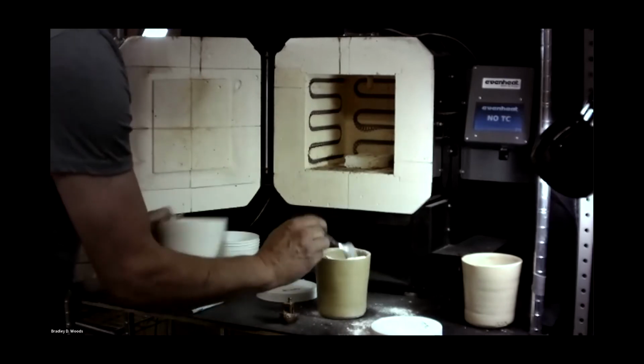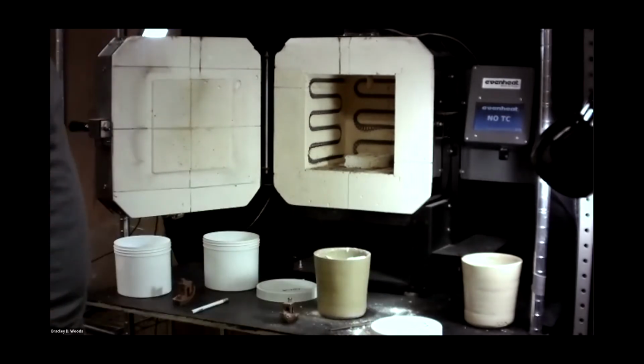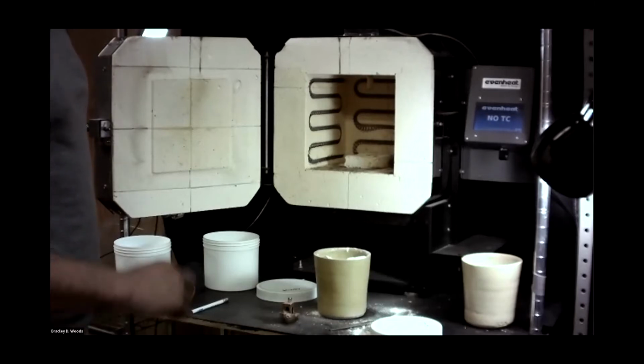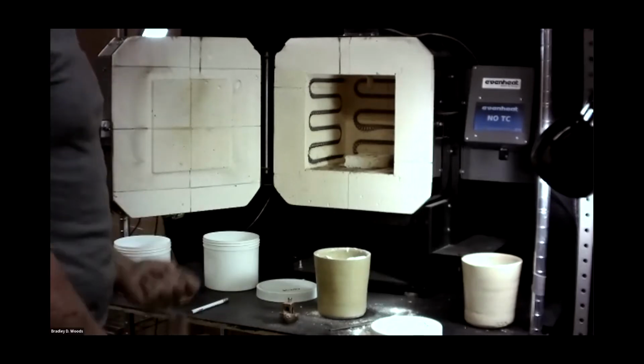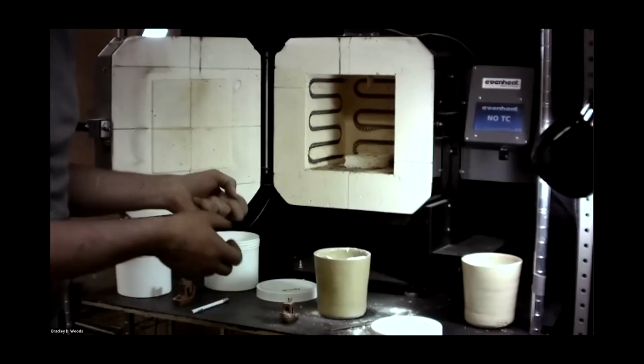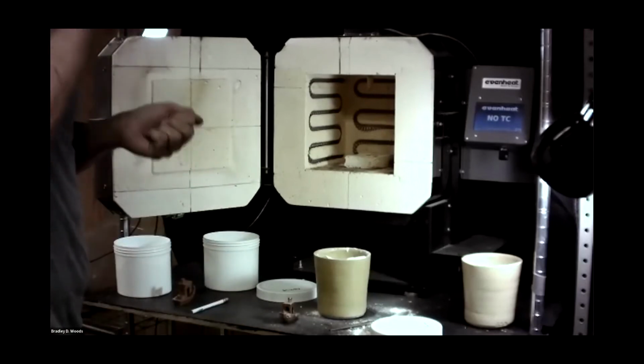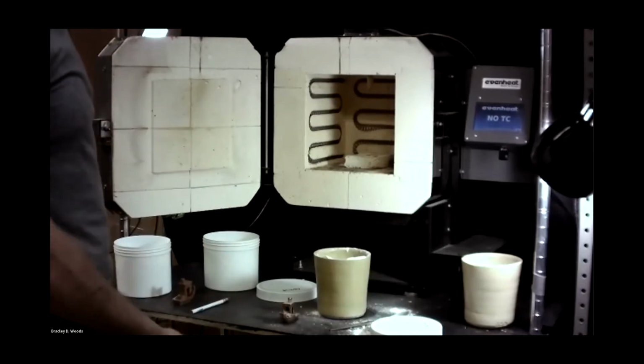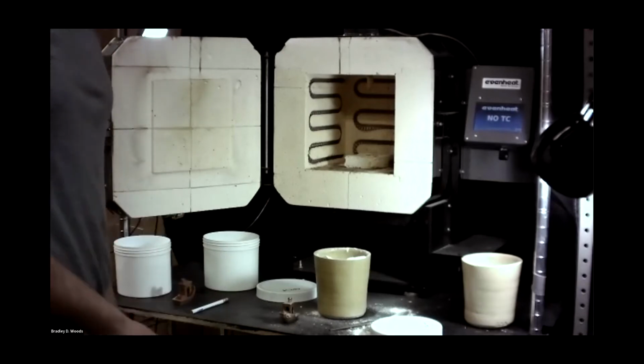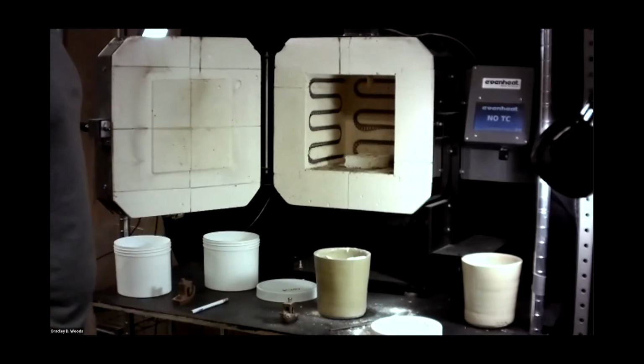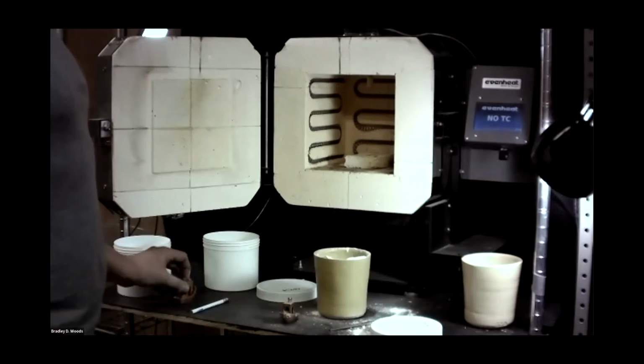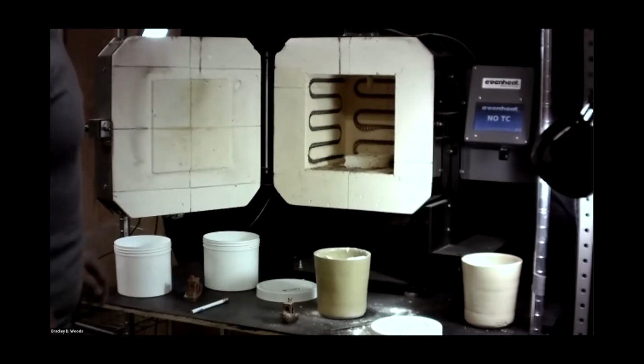Now, Brad, how fragile is that brown part? You're handling it in between the debind and the sinter process. My best answer is it's way stronger than you'd think. You can actually sand on it and clean up the part if you need to. If there's something you don't like about it, it's easily manipulable at that point. If you drop it, it'll break. I would say it's similar to ceramic greenware or clay, somewhere in there, where it's easy to handle, but still fragile.